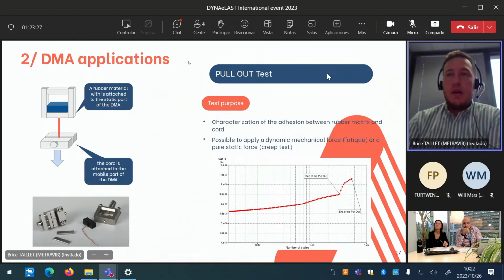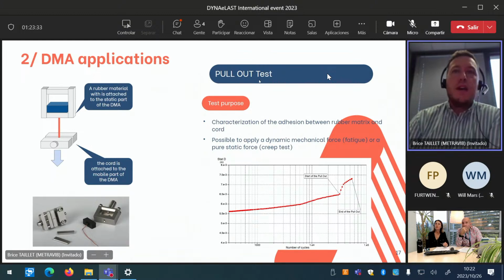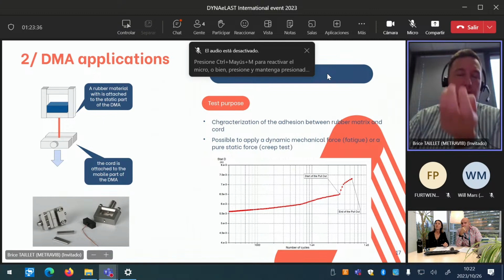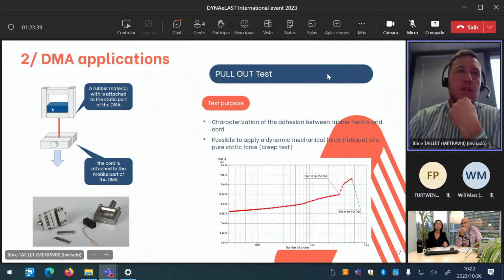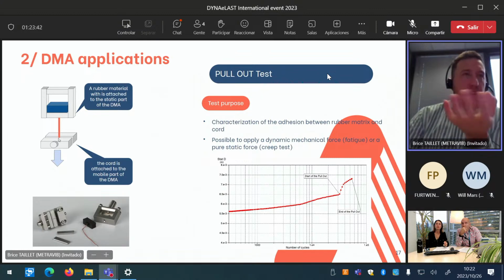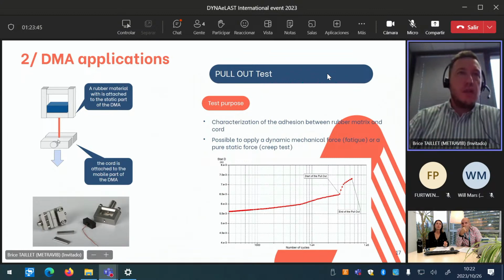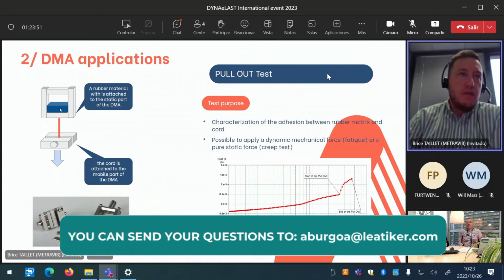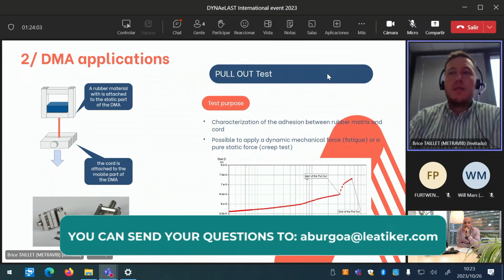Okay. One other, it's quite new for us, the pull-out test. Pull-out test is just the ability to characterize the adhesion between a rubber matrix and cords. This kind of test is mainly focused on the tire industry, once again, but you have the possibility to apply a dynamic mechanical force and a pure static force if you would like to perform a creep test, and to get the static displacement or the static force or the dynamic force between the start of pull out and the end of the pull out test. So it's quite a new functionality available on DMA.